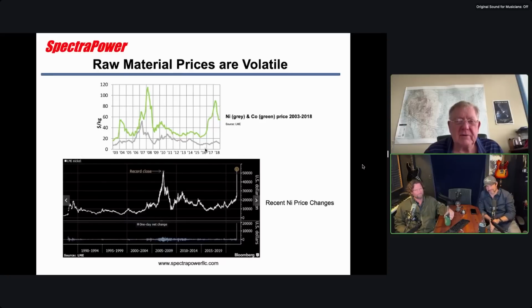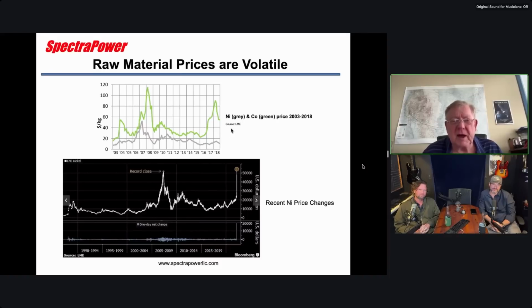So this just shows a history of lithium-ion cathode materials. Cathode is the most expensive component. The gray is nickel and the green is cobalt, at dollars per kilogram. Back in the 2008 timeframe, cobalt was running around $30, $40. And then when lithium-ion really started to come on, especially with Apple putting it in portable devices, the market suddenly shot up because everybody thought this was going to be a huge demand. So it went up to almost 120.